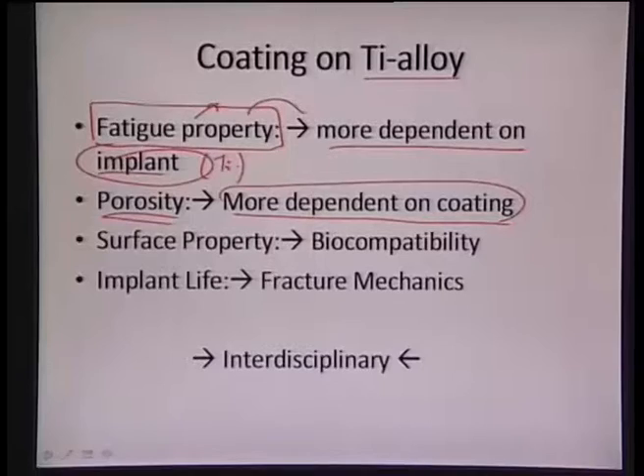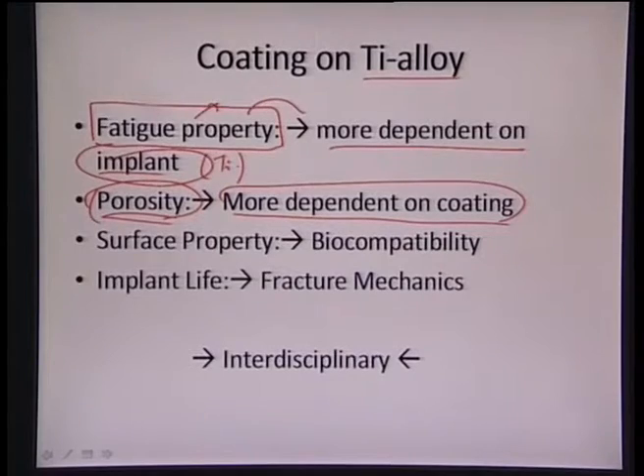So that is a problem with the coating part, and the coating is also mostly decided by the porosity part. We need to have enough porosity that cells can come and adhere onto the surface, cling themselves onto the porosity which is available to them, and then form a strong bond with the bone implant. So that is one more criterion, that we need to have a good porosity which is similar to the size of the cells, and that can provide anchoring to the cells.